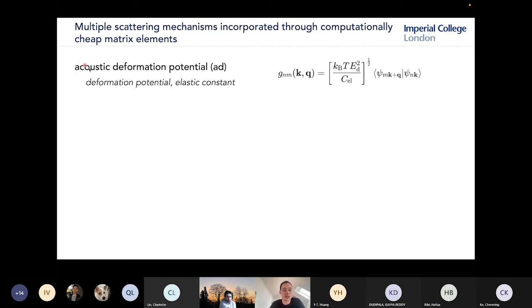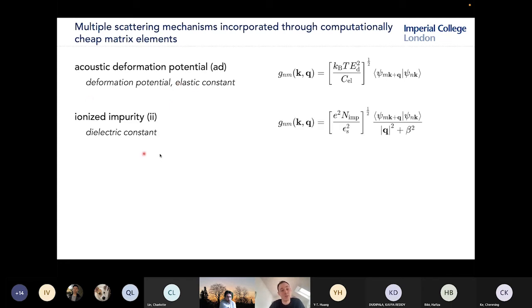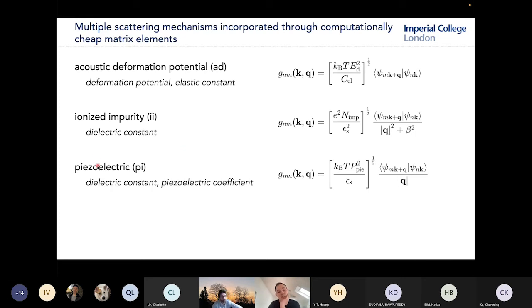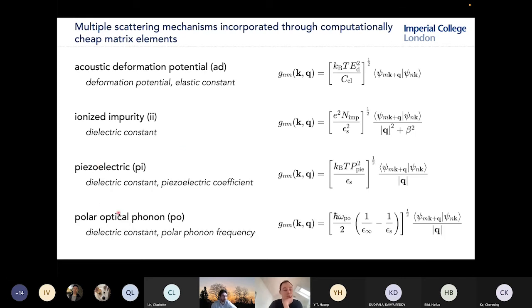For example, acoustic deformation potential scattering, which depends on the deformation potential of our material and the elastic constant. Impurity scattering, which depends just on the dielectric constant. Piezoelectric scattering, and also polar optical phonon scattering, which depends on the dielectric constant and phonon frequencies. Now, all of these properties that I mentioned that you need to calculate these matrix elements are really readily obtainable just from routine first principles calculations. So none of these are expensive to obtain.